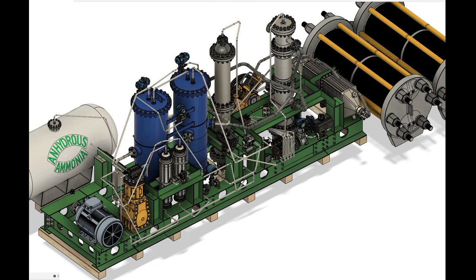For 1 ton of ammonia, 822 kilograms of nitrogen is required, so the PSA system would use 98 kilowatt-hours per ton of NH3. The synthesis gas compression emerges as the second most energy-intensive step in the ammonia synthesis process after hydrogen production. For centrifugal compressors installed on extant large-scale plants, the compressors draw 25,800 kilowatts of power for a 2,200 metric ton per day plant operating at 200 bar,